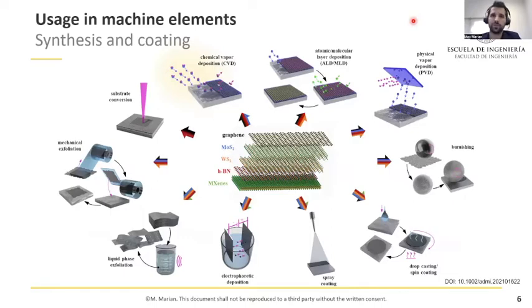So when thinking about testing in an application-oriented context, we also have to think about how to produce the 2D materials, how to synthesize them, and how to deposit them on our components, for example bearing rings. This slide shows different processes, and the color coding assigns the different 2D materials to the possible or so far researched deposition processes. Regarding MXenes, they have to be synthesized from MAX phase by liquid phase exfoliation, which I will show in a moment. Then they can be deposited on the component using relatively simple methods, like drop casting or spin coating, or some advanced techniques like spray coating or electrophoretic deposition.